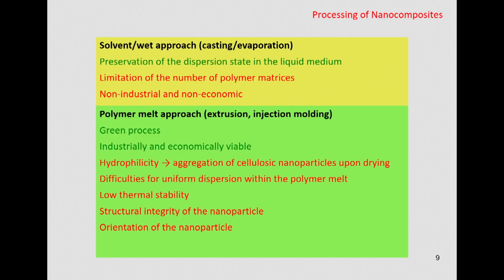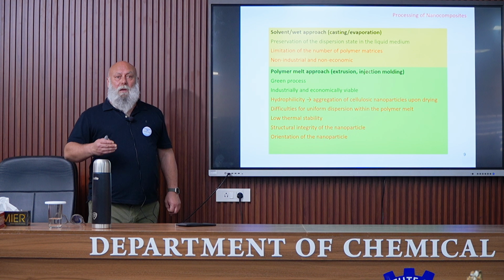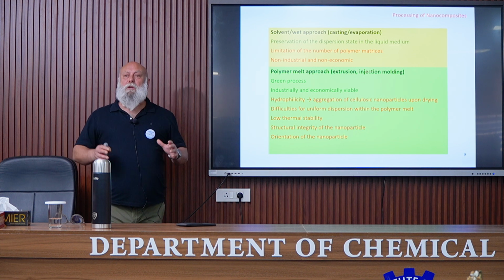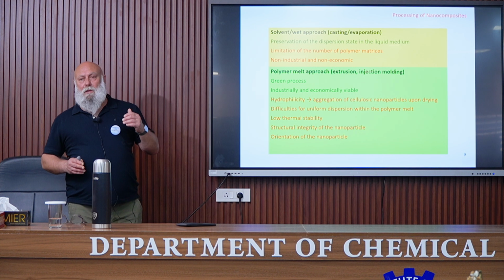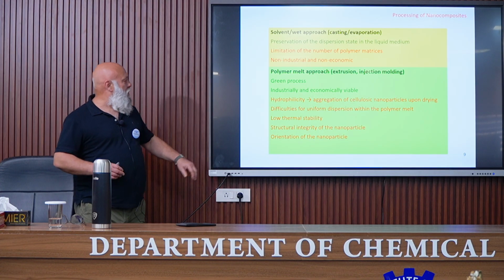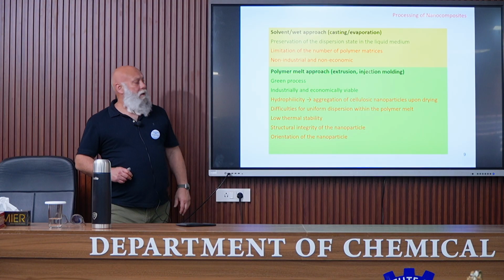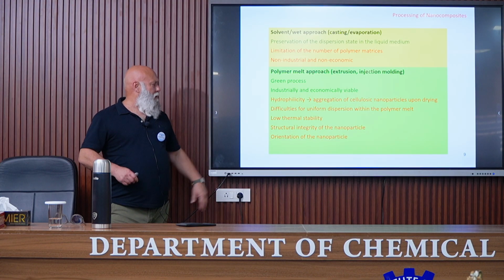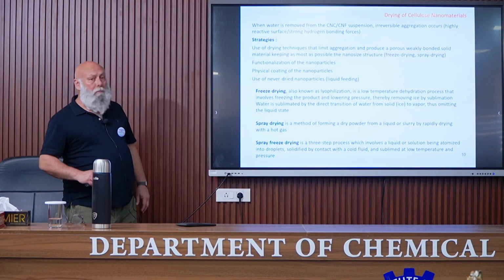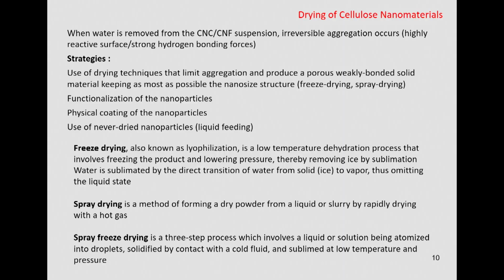A problem can also be the low thermal stability of cellulose, mainly for cellulose nanocrystals, because we'll see that for cellulose nanocrystals, usually sulfuric acid is used. It is good to have a stable dispersion, but the presence of the sulfate groups decreases the thermal stability of cellulose. Structural integrity of the nanoparticles we'll discuss, and the orientation. So, we'll see each of these drawbacks, and I will show you the possible strategies to avoid these problems.